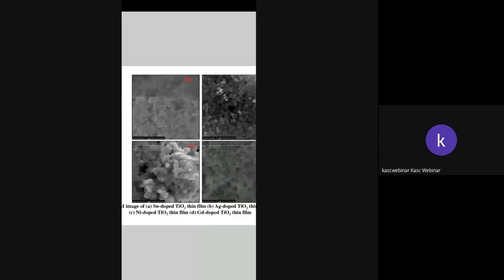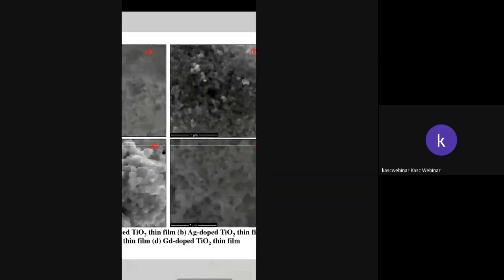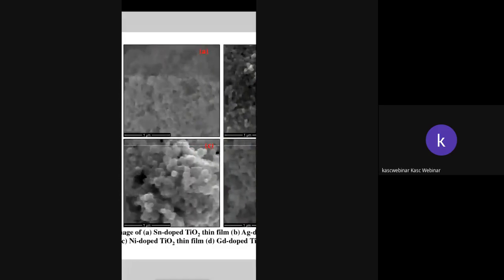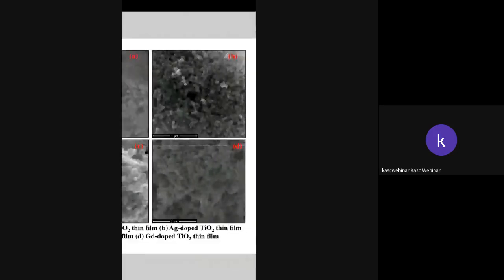The first, A, represents tin doped TiO2, B represents silver doped TiO2, C represents nickel doped TiO2, and D represents gadolinium doped TiO2. We have obtained a very good homogeneous film. This has been inferred from the SEM analysis.